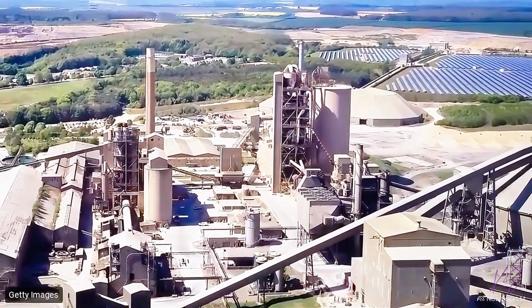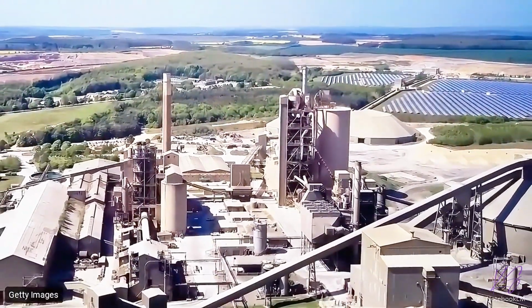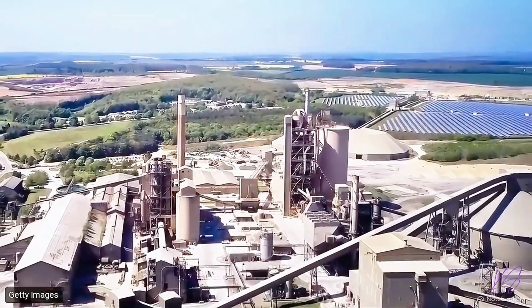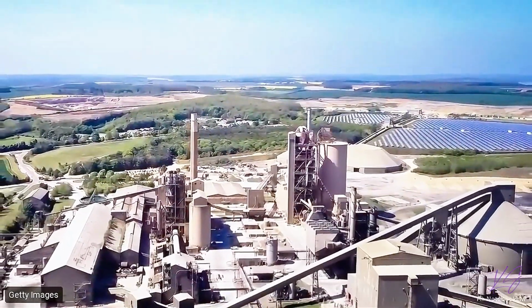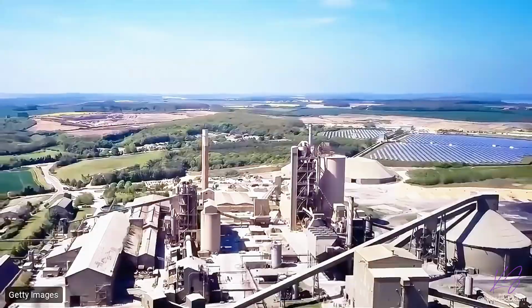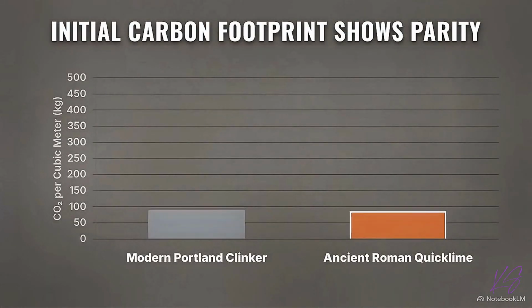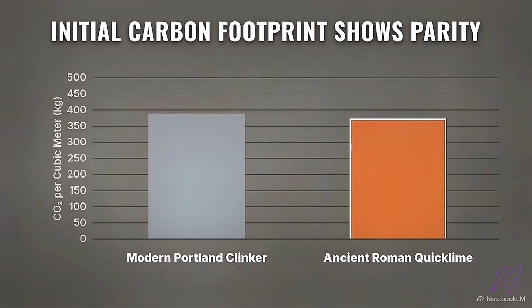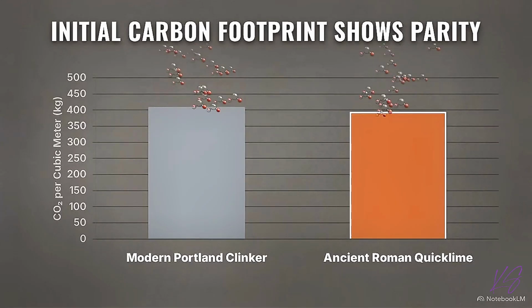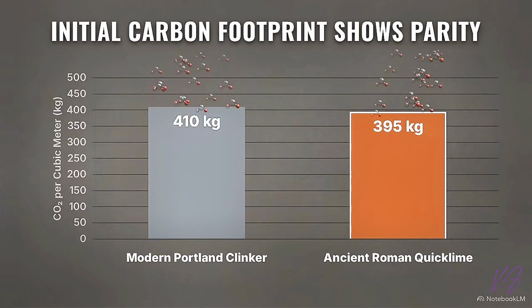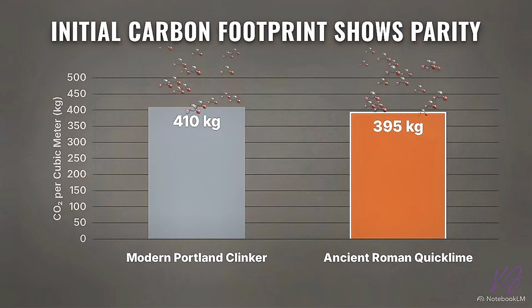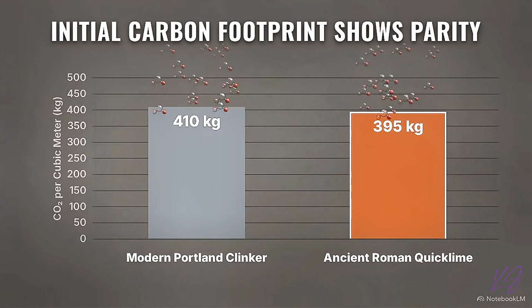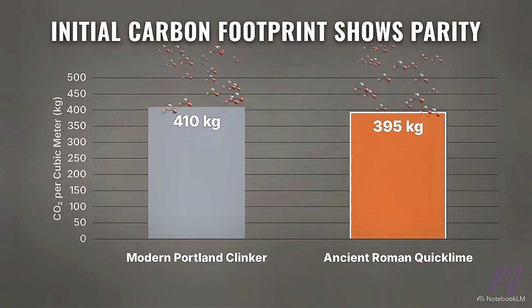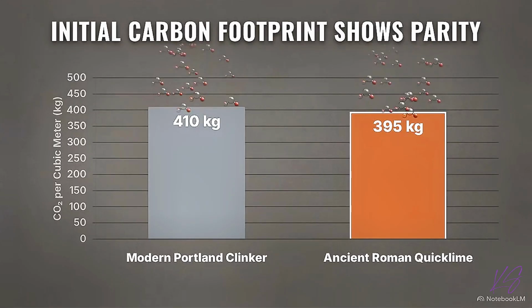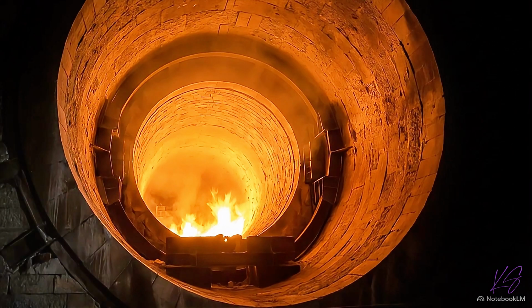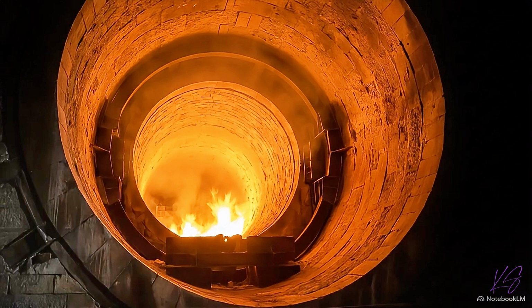The search for alternatives is urgent. Global Portland cement production is an environmental behemoth, responsible for roughly 8% of all greenhouse gas emissions. This chart shows the initial carbon footprint of both materials based on a 2025 life cycle assessment. Producing Roman quicklime still requires calcining limestone in kilns at nearly 900 degrees Celsius, off-gassing nearly identical volumes of carbon dioxide per cubic meter as modern formulations. The Roman recipe is not a low-carbon miracle at the factory gate.